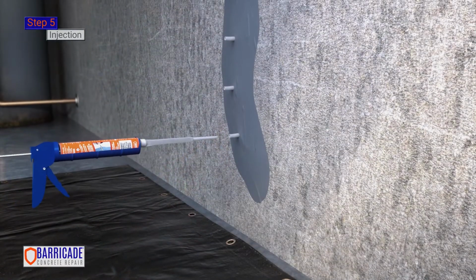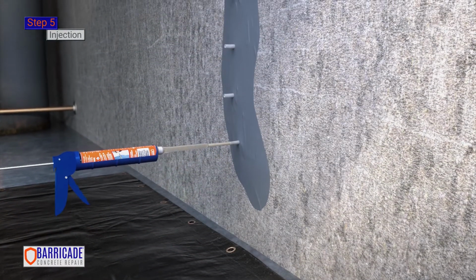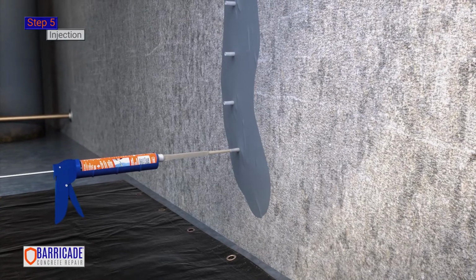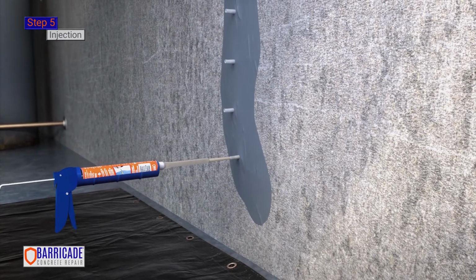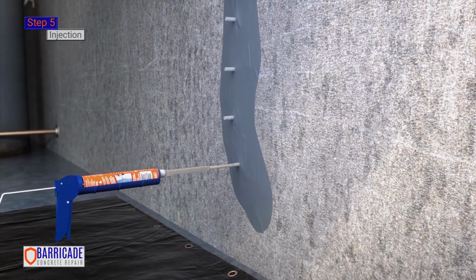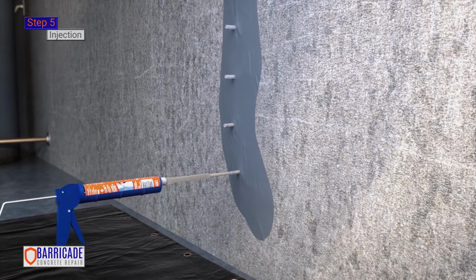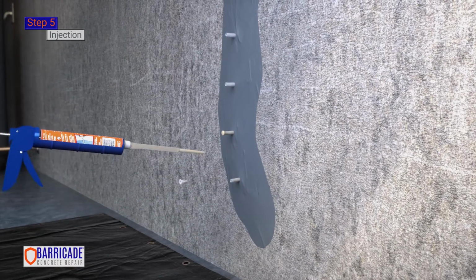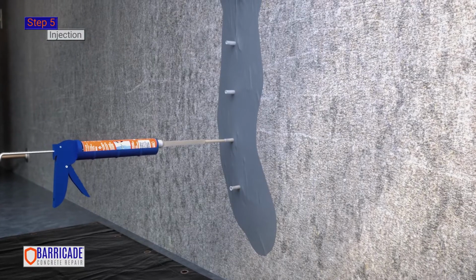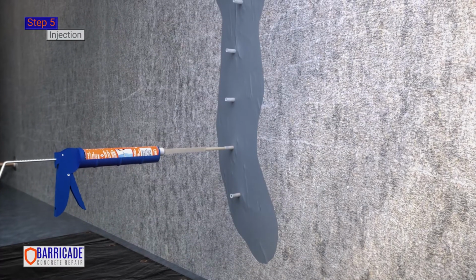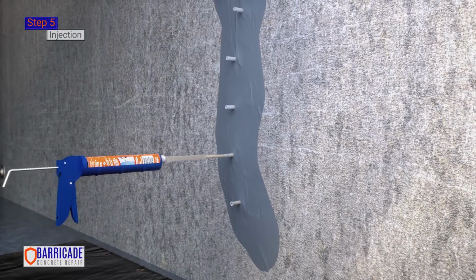Starting at the bottom port, push the static mixing nozzle into the port until you feel a click. Dispense the product slowly until you see it coming out of the next highest port. Remove the nozzle and close off the port with the cap. Please note that injection may take up to 4 minutes or longer per port. The tighter the crack, the longer the polyurethane will take to flow into it.